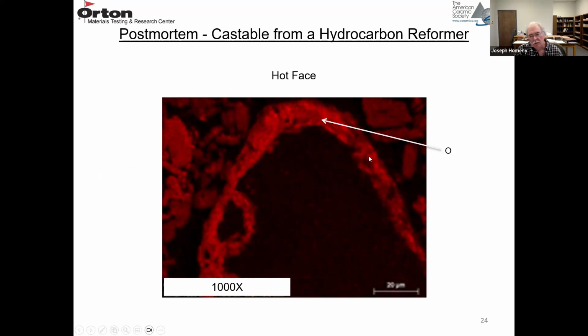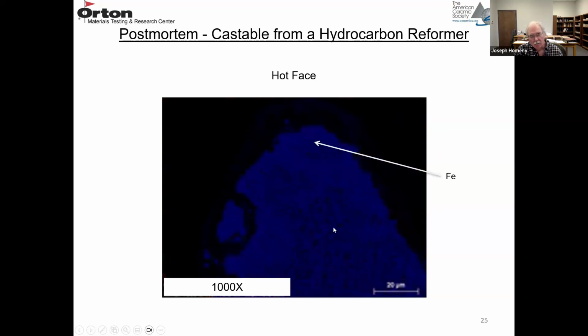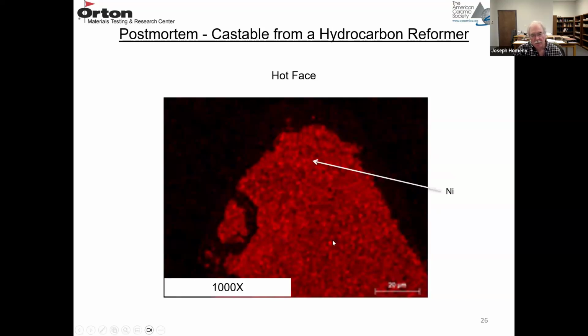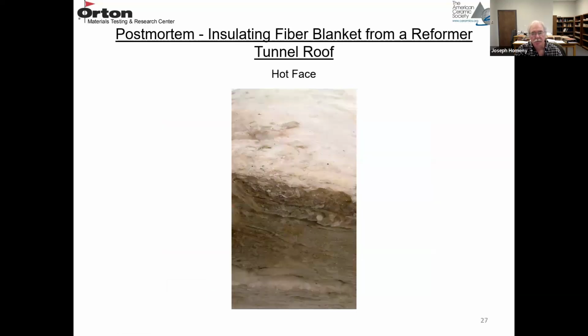And then here's the oxygen in red. So you can see it's formed this oxide layer, mostly Cr and O. And then this is the oxygen in the aggregates outside of this fiber. And I also mapped Fe in blue. So the layer is on the edge here. So the iron does not diffuse out of the stainless steel, and neither does the nickel here in red. Just the chrome is diffusing outward and oxidizing. So that was a castable with a metal reinforcement.